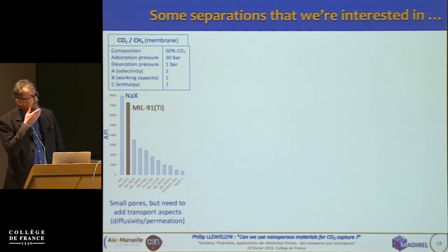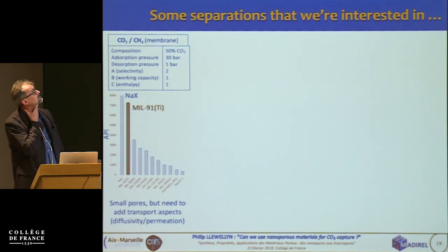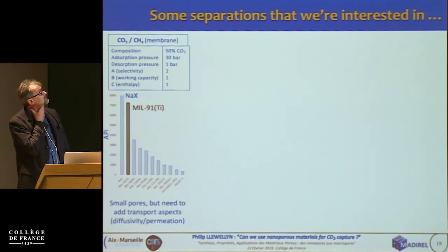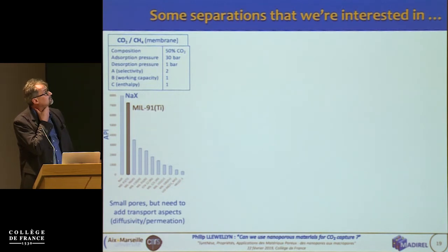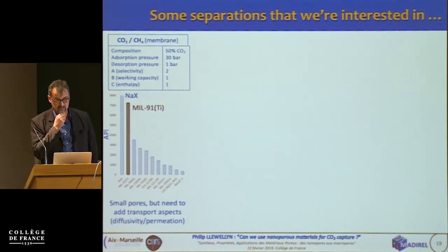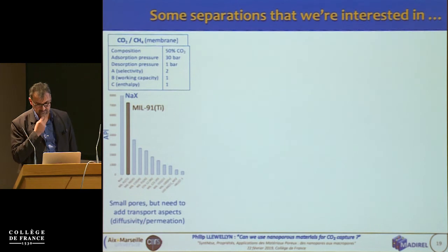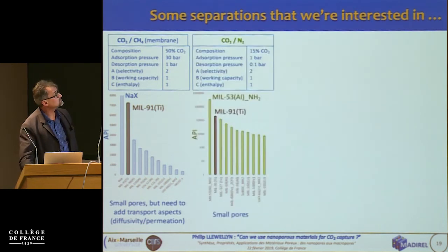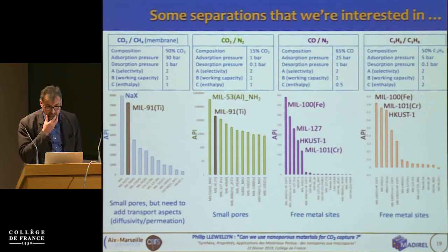So these are another series of experiments. This is CO2 from methane. Sodium X seems the best, but you'll find later that things with zeolites have problems with water, for example. Other small pore materials, so both of these seem to show that MIL-91 is of interest. And then we go to other separations, for example, CO2 from nitrogen, or propane from propylene. We'd like to have maybe free metal sites. So these are the materials that come out. So, fine.